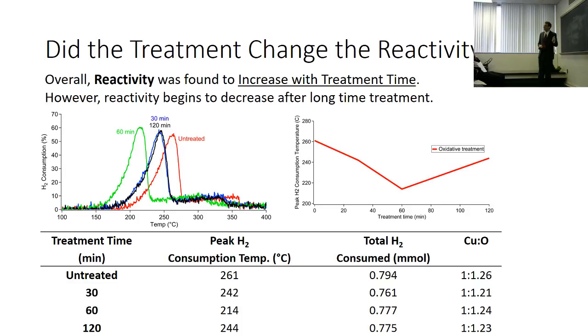What you would expect for copper oxide—so I loaded a known amount of copper oxide, so I know how much copper was there—is 1-to-1 copper to oxygen. But what I found was actually, in these materials, it was 1 to 1.25-ish. Too much oxygen. Maybe it's on the surface.